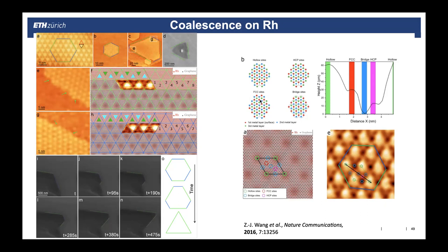And actually you have to look at the three topmost layers, because you have hollow sites where you can put the carbon atoms, you have bridge sites and so on. And there are different coupling strengths. And in the end, you end up not attaching atoms individually, but really you always attach a moiré unit one after the other. It's a bit more complicated. But we studied all this in detail, I think this was also done by Chushun. He really combined in situ STM and all these kinds of things to really understand how you can make from individual islands a continuous